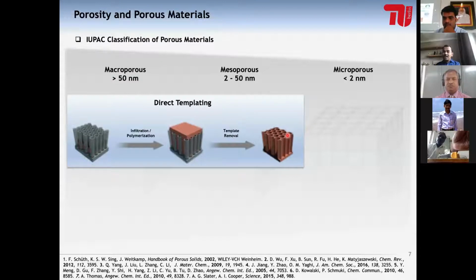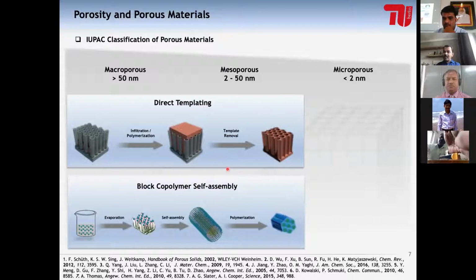composition. Similarly, many of us have heard of block copolymer self-assembly, wherein you have different micelles which get organized in a particular fashion, giving out polymeric materials, carbons as well as porous materials, including silica, carbon, and so on and so forth. Since these materials work in the macroporous and mesoporous region, what we generally see is that direct templating as well as block copolymer self-assembly work very nicely, because the pore size is beyond 2 nanometers, up to 50 nanometers, 100 nanometers, close to that region.